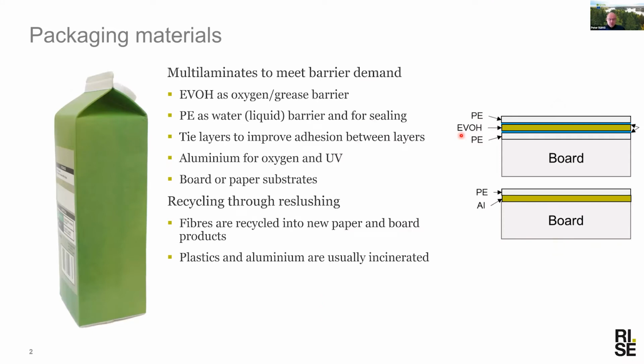If we look a little bit at the background, if we look at fiber-based packaging materials, you usually need to put on a barrier in order to either protect the content or to protect the board material itself, since it's quite moisture sensitive. That means you usually need both an oxygen barrier and a moisture or water barrier, and that tends to become tricky. You either put an aluminium layer combined with a polyethylene layer, where the polyethylene is more or less for heat sealing, or you have a multi-laminate consisting of polyethylene and some other plastic that makes a very good oxygen barrier, like EVOH.